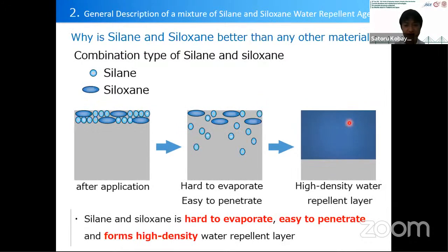This is a combination type of silane and siloxane. After applying this type of water repellent agent, silane is easy to penetrate and siloxane is difficult to evaporate. So it formed a very thick, high density water repellent layer like this. So why are silane and siloxane better than any other materials? That is the answer.